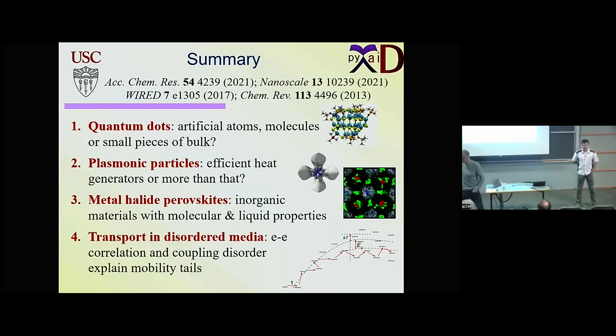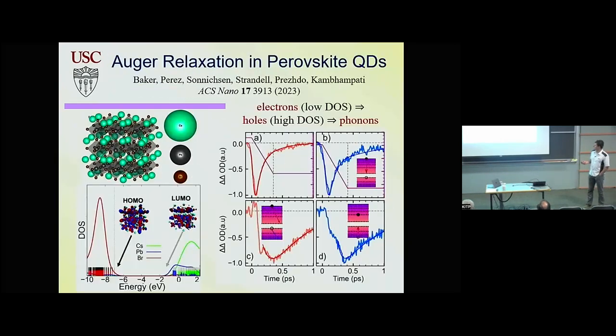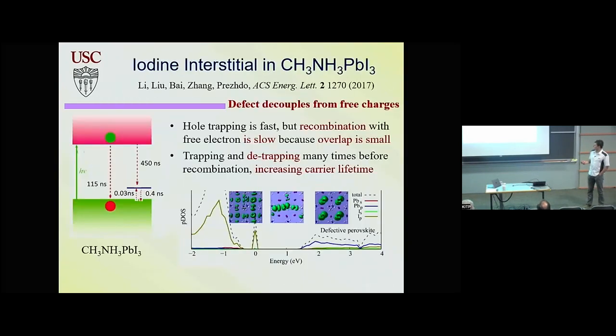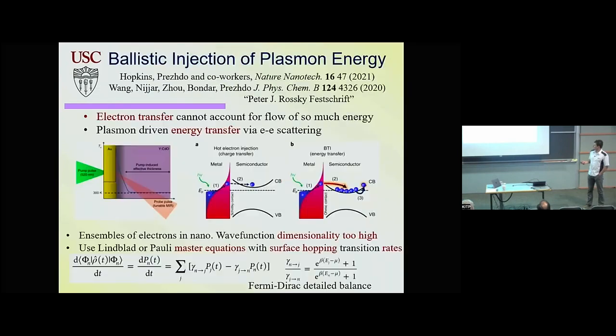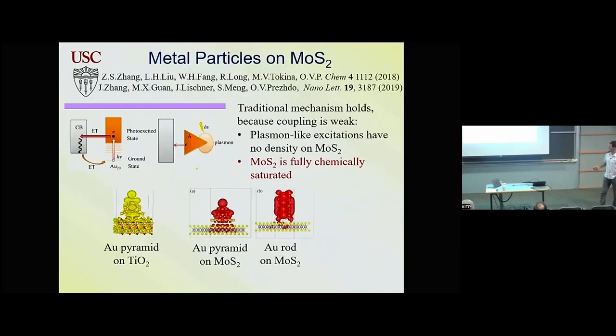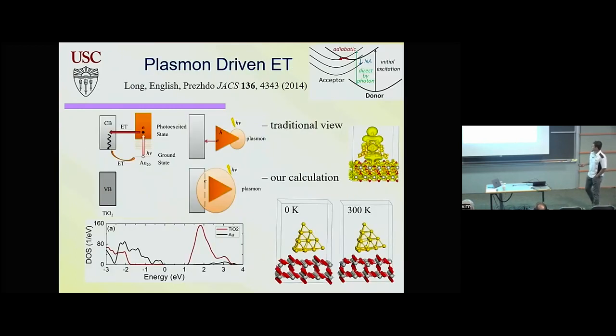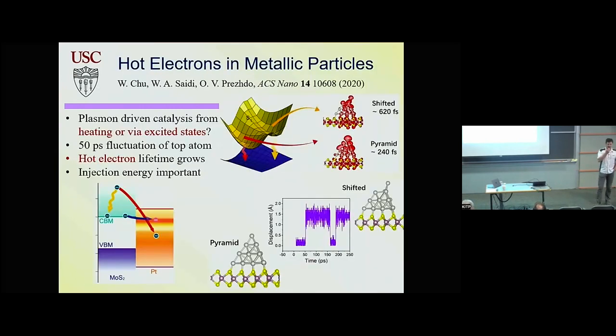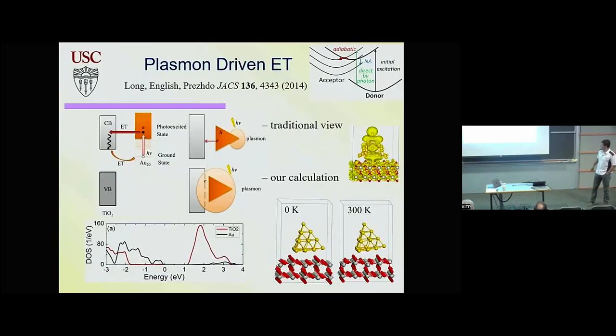I want to ask about the semiconductor-metal hybrids with a PICT mechanism. A comment: usually for photocatalysis, we need to excite the semiconductor and then get the electron to the metal. Not this one. Yeah, not this one, right. But the idea there is that you can excite the metal and still get a hot electron into the semiconductor. Right. Actually, you have to compete with very fast relaxation and back transfer to the metal. We saw that with this very elegant mechanism, but you have to extract that electron within like 100 to 200 femtoseconds to avoid the back transfer.